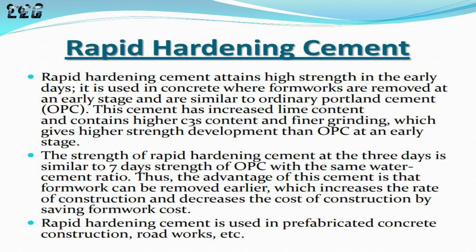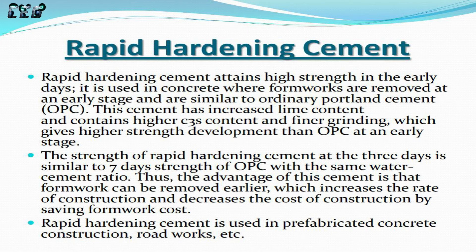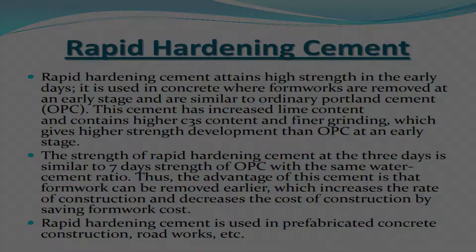The strength of Rapid Hardening Cement at 3 days is similar to the 7-day strength of OPC with the same water-cement ratio. Thus, the advantage of this cement is that formwork can be removed earlier, which increases the rate of construction and decreases the cost of construction by saving formwork cost. It is used in prefabricated concrete construction and roadworks.